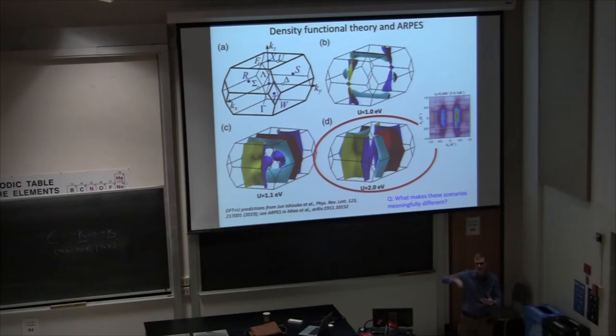All I really want to draw attention to is that this scenario has relatively flat bands at the Fermi level — this one too, this one too. This one doesn't; the bands all have a slope where they hit the Fermi level. Slope is the group velocity of the particles. These are particles that travel fast at the Fermi level. These have particles that travel extremely slowly at the Fermi level, which makes it very easy to incorporate them into density waves. So this scenario — with parallel sheets and very slow-moving particles — would really want to be a density wave material.